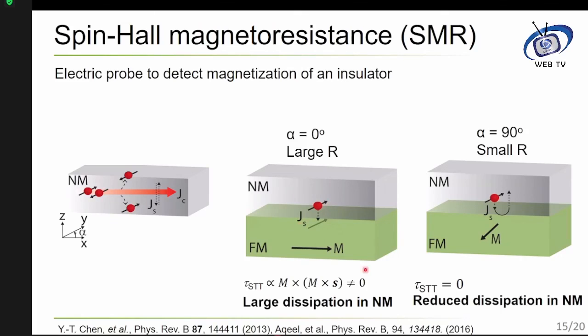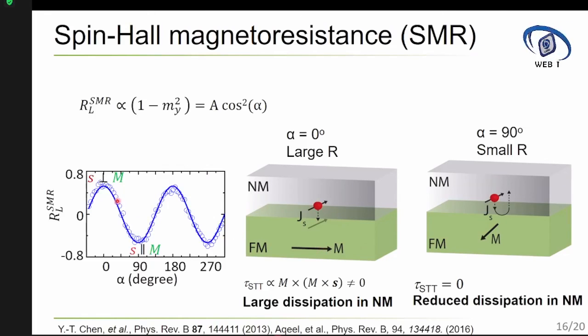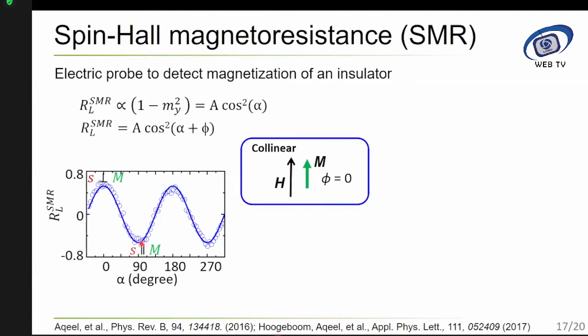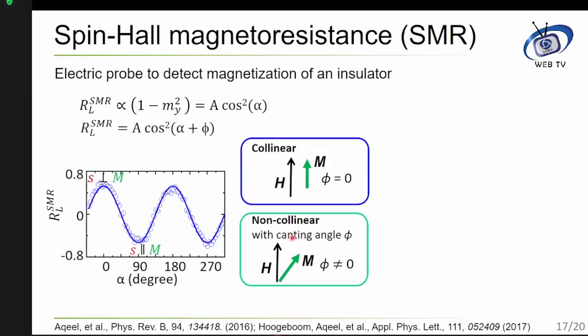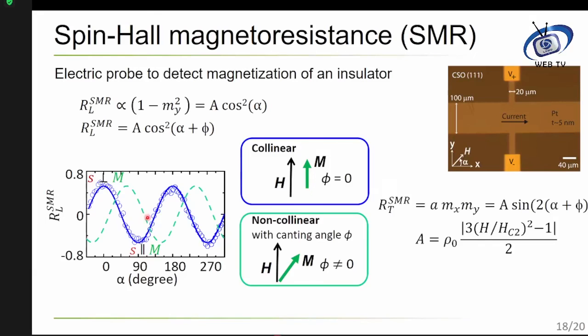With this, we just measure the resistance of the platinum metal, and we can tell the underlying magnetization direction. You expect the resistance of the platinum to have a sinusoidal dependence. Where it's perpendicular, the resistance will be large. Where it's parallel, the resistance will be small. Now, the unique thing is that our magnetization doesn't align parallel to the magnetic field all the time. It has a texture, so you expect changes in this periodicity. There is a lot of mathematics, but the idea is very simple. Whenever the electron spin in platinum is parallel, it will be small resistance, and when it's perpendicular, it's high resistance, and you can tell if there is a texture or not.